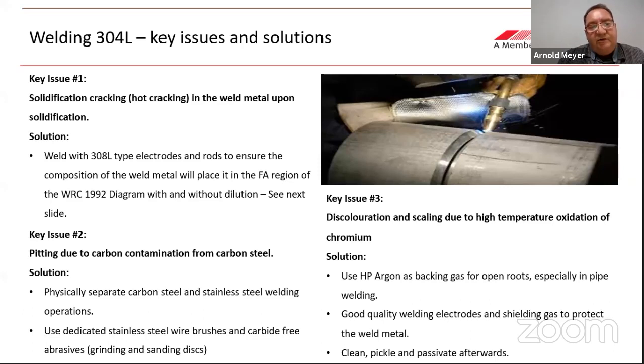The second issue is pitting due to carbon contamination from carbon steel. And the third one is the discoloration and scaling due to high temperature oxidation. And that's the discoloration that Simon referred to. The solution for the solidification cracking of 304 is to weld it with a 308L type electrode.